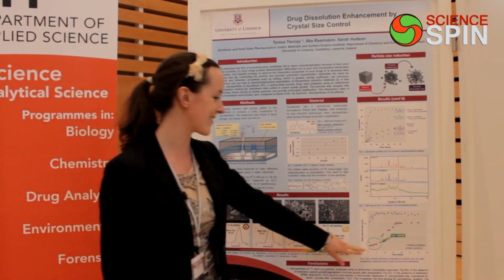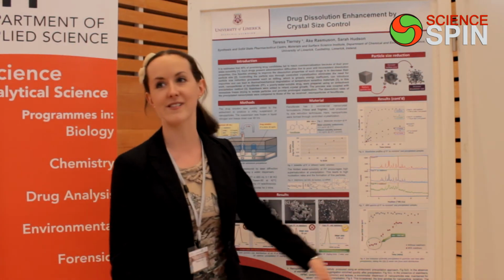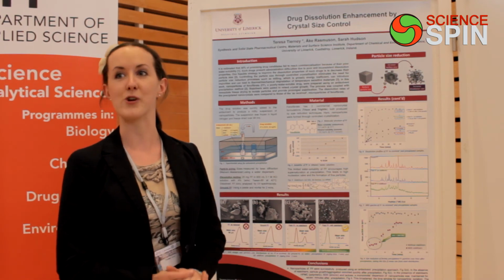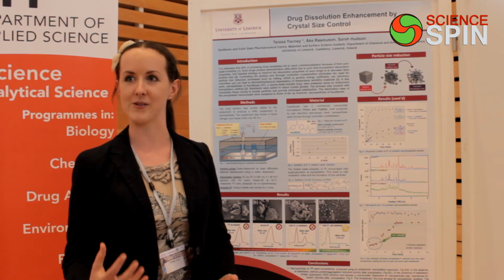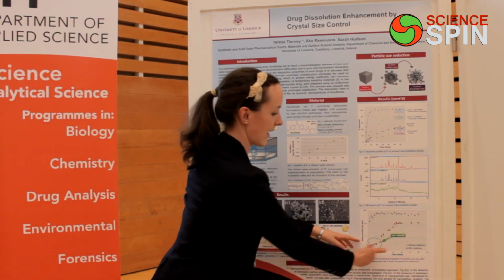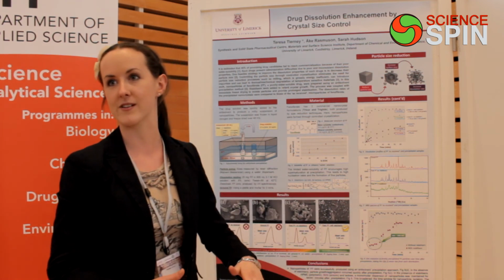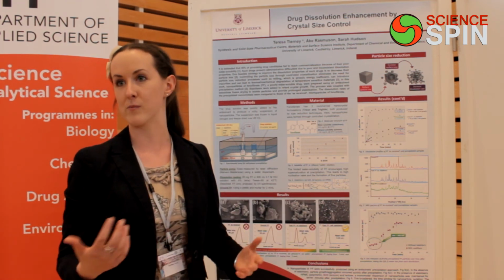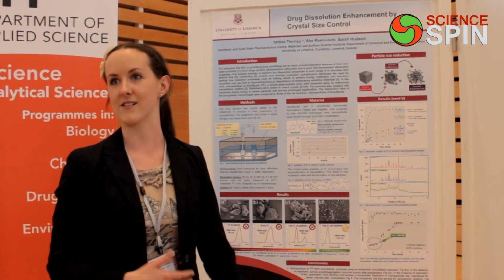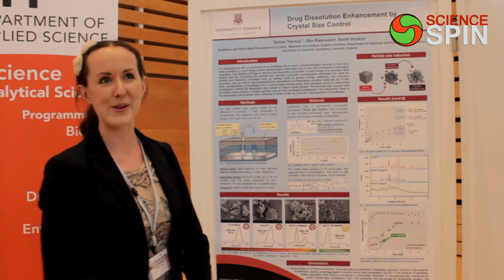I've shown in this graph that I can only stabilise my nanoparticles for about 10 minutes. That means I need to dry them really fast before they have a chance to grow out of the nano size range. So the big part of the project at the moment is trying to extend the period that they are nanoparticles. If it was on plant scale, it would give a better chance to isolate the nanoparticles while they're still nano. So there's a little bit more work involved.